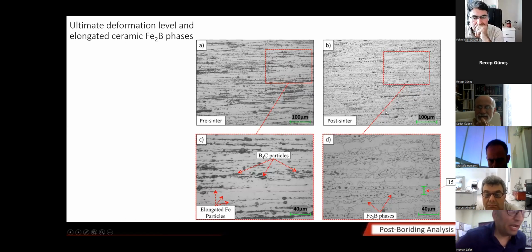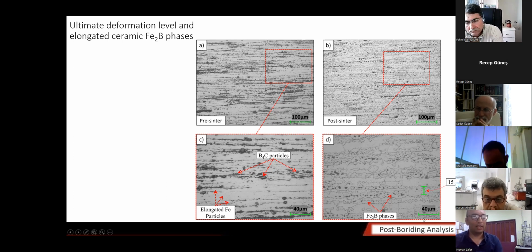Here is again the ultimate deformation in the 1 millimeter wires. These iron particles were not agglomerated anymore. This is the S15 specimen, which had shown the formation of agglomerated B4C particles. But even at micro scale, this is 15 micrometer, we can see iron boride phases elongated parallel to the direction of the cold rolling. We can call them ceramic fibers because they are very small at the fiber scale, and you can control their morphology, and you can also control their distribution by using an appropriate reinforcement ratio in the pre-sinter state of the wires.